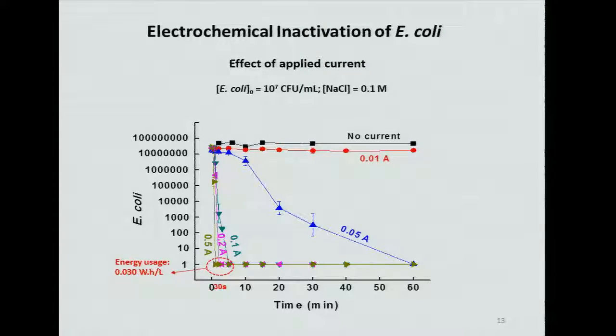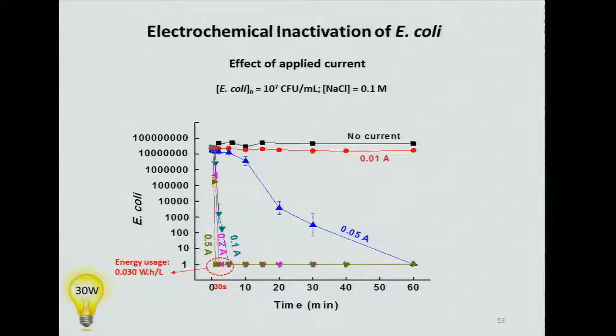And that's very fast. And the energy usage for this inactivation was about 30 milliwatt hour per liter. How much is this energy? This is like you turn on a 30 watt lamp for 3.5 seconds, which is not that much.